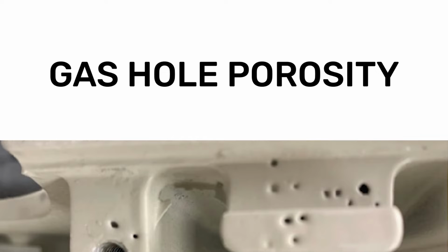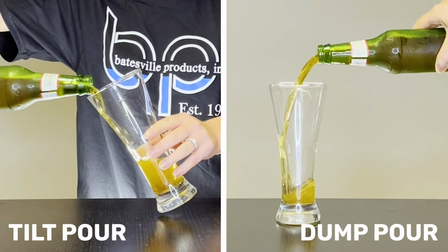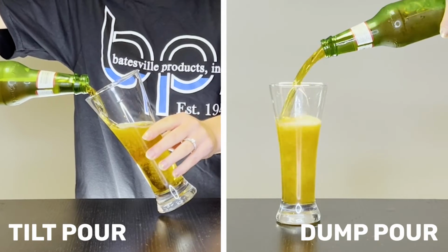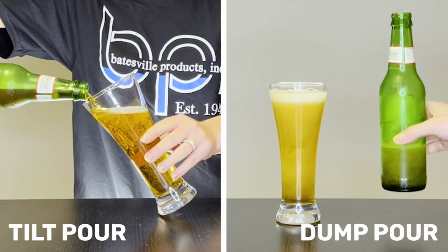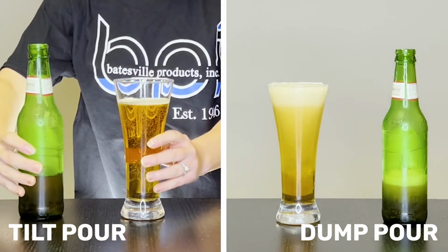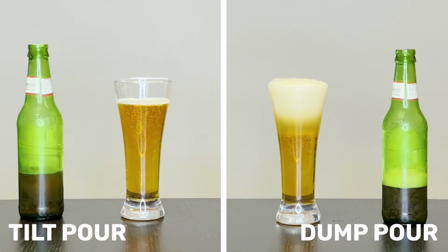Gas hole porosity is caused by metal turbulence. Basically, the metal is rushing into your mold at too high of a velocity, sloshing around and trapping air bubbles. If you're experiencing gas hole porosity, you need a better designed pouring and gating system. Dump pours, or when the metal is directly dumped into the mold without a good gating and riser system, can create a lot of turbulence, which creates a lot of porosity.